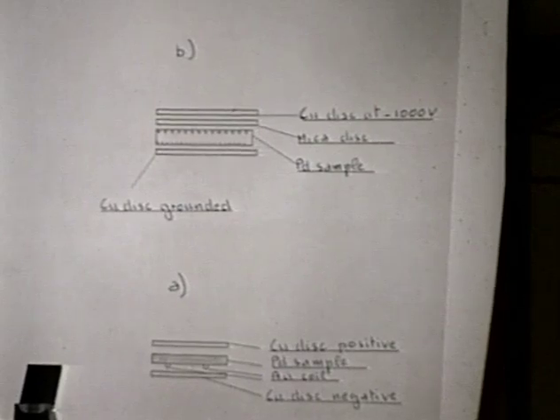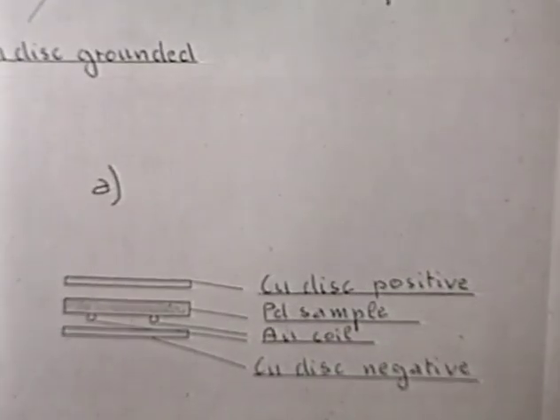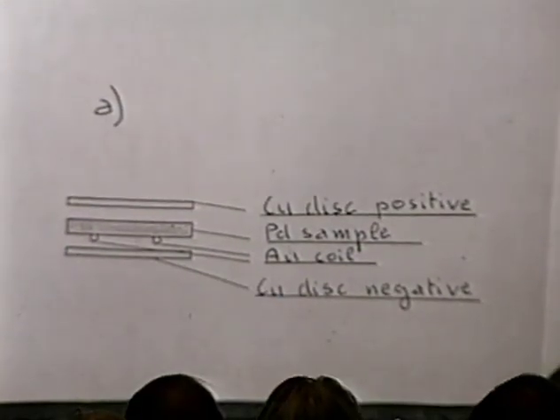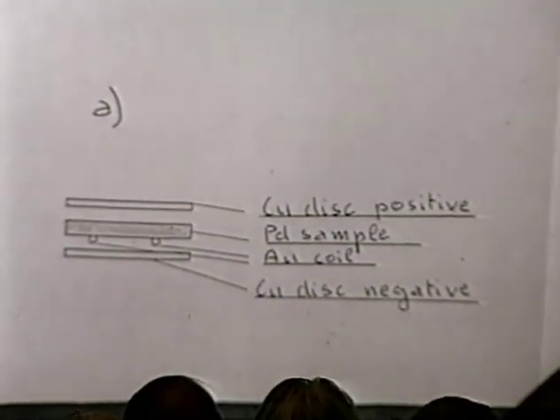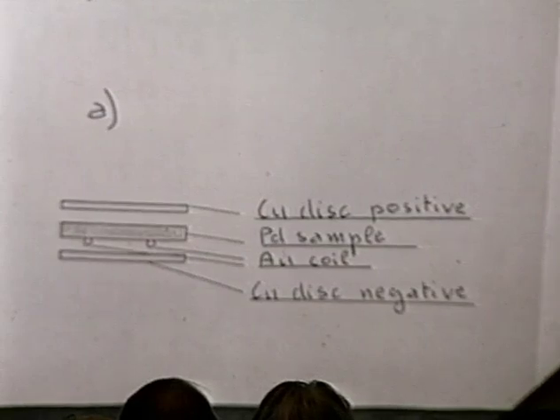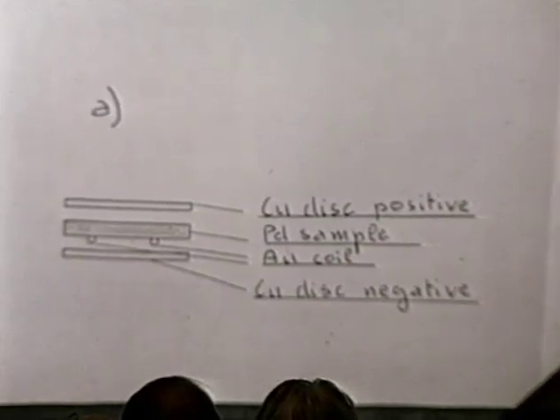This was a hope. Probably this was not the better design, because the length in which we have a gradient is surely small. Anyway, the system was working, because now we think that when 1 ampere or 2 ampere were crossing the sample, probably at the contact you have a discharge of deuterium, and so you are creating inside the sample a gradient due more than to migration to diffusion from the discharge of deuterium.